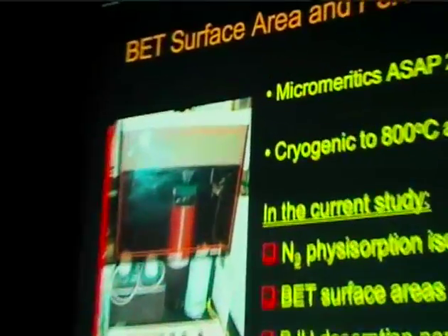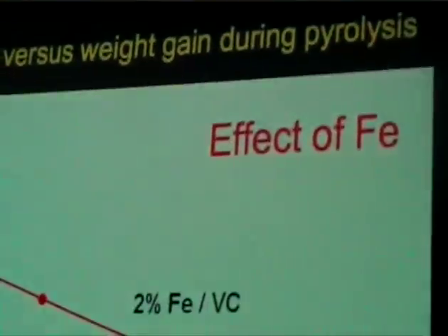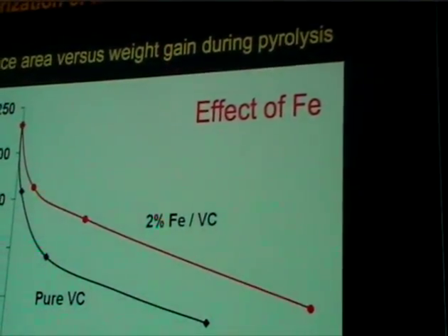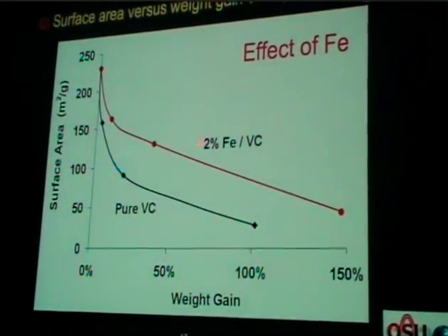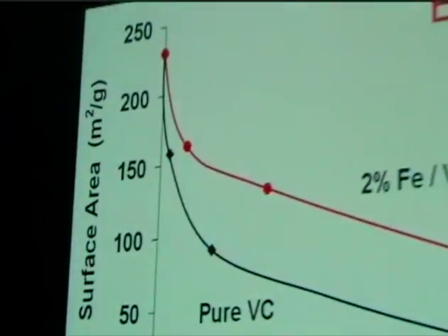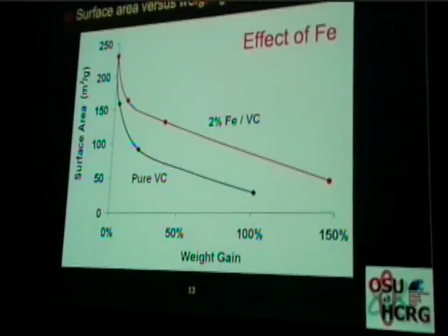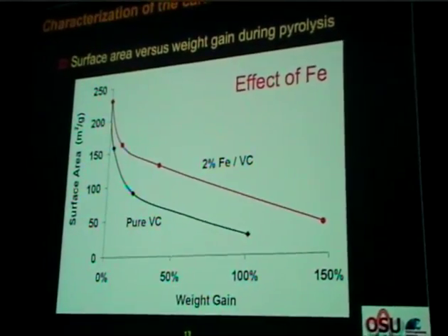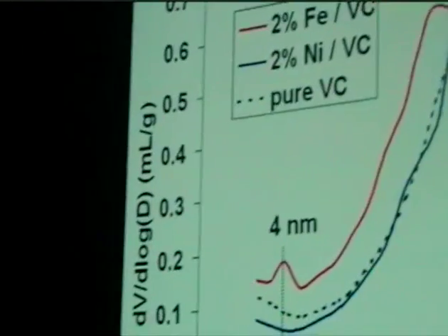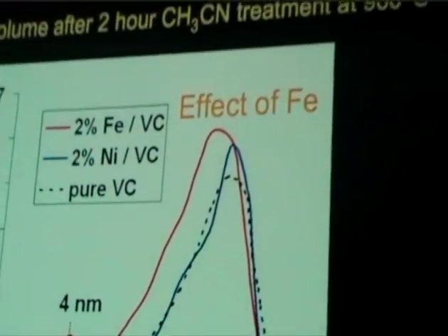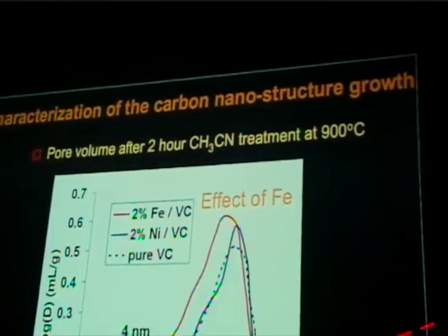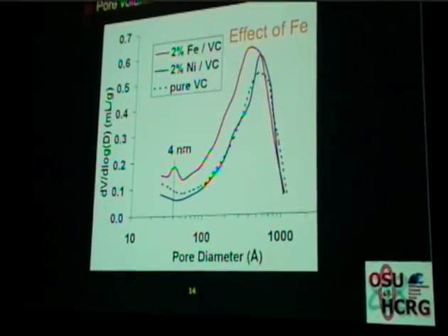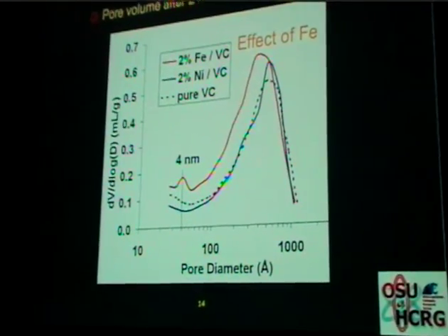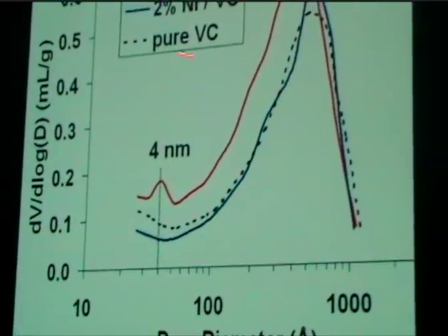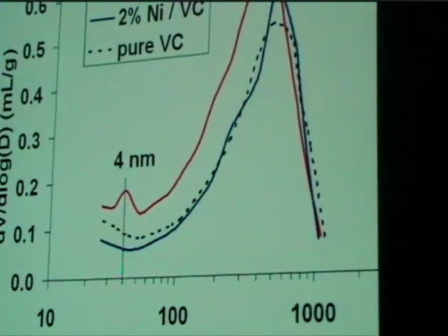If we look at the surface area and pore volume of these materials, for any weight gain, the iron-containing Vulcan carbon allows carbon structures to grow with higher surface areas. When we look at the pore size distribution, the red curve represents the carbon structures grown on iron-doped Vulcan carbon. What we see here is a pore size around 4 nanometers, and we don't really see it on carbon structures grown on pure Vulcan carbon or nickel-containing Vulcan carbon.